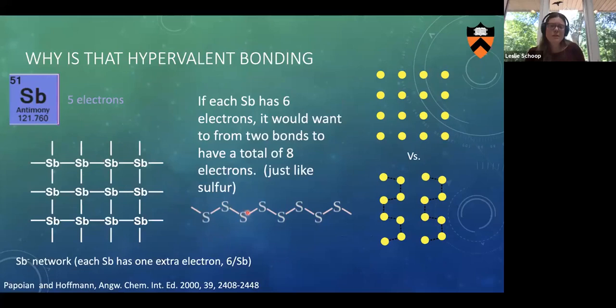Elemental sulfur forms these zigzag chains, one conformation of it. But in antimony, we have six electrons, and in addition, we have four bonds. So they would add up to 10 electrons if you counted them as two-electron, two-center bonds, the same electron count as in phosphorus pentafluoride. And the only reason we can stabilize this is not by having more than eight electrons in the shell, but by delocalizing these electrons over this whole sheet.